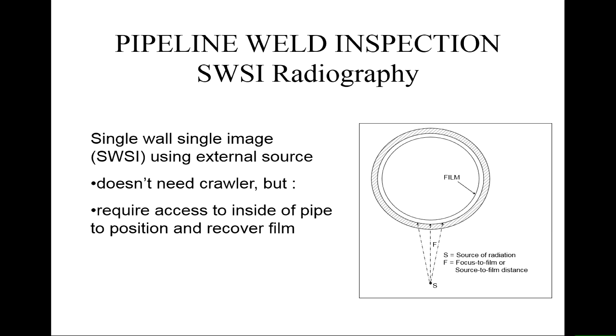So this is a single wall, single image case. That means if the source is on this side, you're getting images on the film here, and then the X-rays are passing through, and you're getting images on the film on the other side as well if you're not careful. Obviously, you need to know what the focus to film distance, or source to film distance, is, and the defects on the front end of the pipe will be much more apparent than the ones on the back side of the pipe. So you might have several source positions to do that. Obviously, you need access.